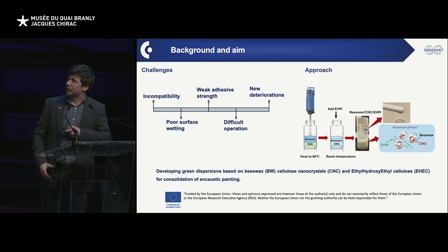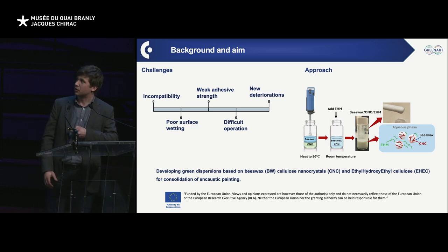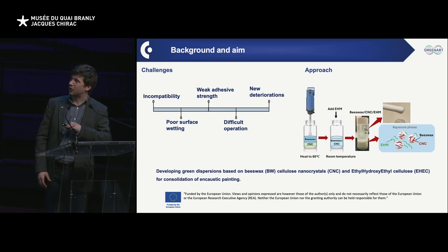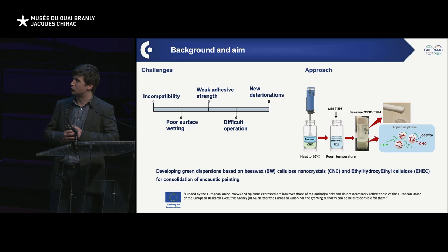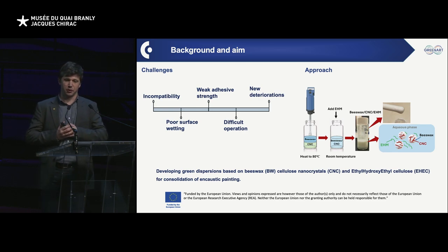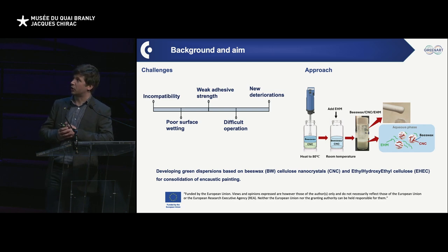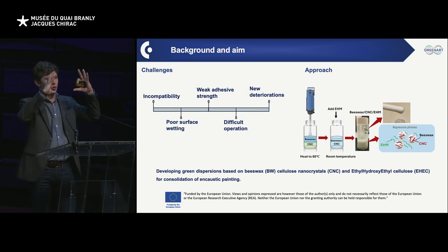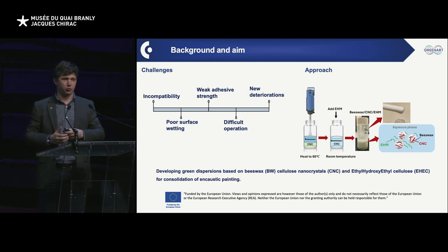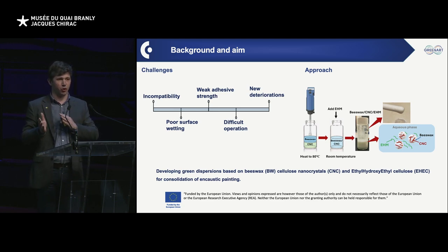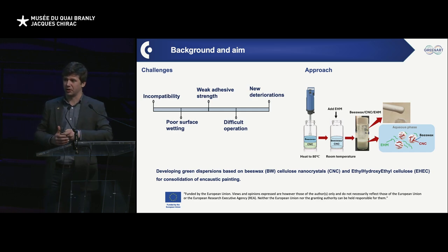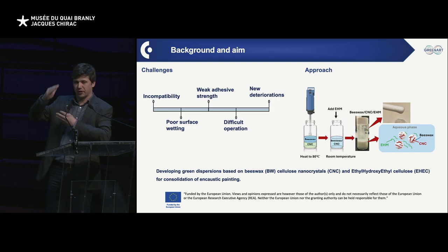So on the right-hand side, you have basically the approach that we have been taken. It's relatively simple, but that's here that kicks in the nanocellulose and the cellulose nanocrystals, essentially. Because historically, we have been working extensively on showing that, yes, with cellulose nanocrystals, and if you play a little bit with the colloidal properties of this type of particles, you can emulsify a lot of different things. And in that case, we can just melt the beeswax, make an emulsion stabilized by CNC, so essentially we have a droplet of beeswax that is fully covered with cellulose nanocrystals, so in a way we solve the incompatibility problem, because the beeswax and the CNC, they can like each other to some extent. CNC is a colloid that has some facets that are hydrophobic, and if you place them properly, that could work.